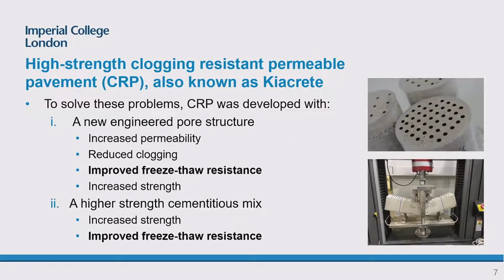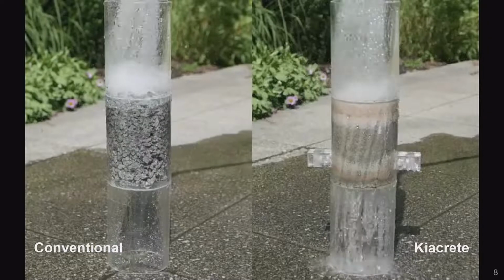So in order to address these two challenges, and also the freeze-thaw, which I will mention in a moment, we developed a new type of permeable pavement, which is called clogging resistant permeable pavement (CRP), also known as Kiacrete. So we completely changed the pore structure of this type of pavement. So we engineered a new type of pore structure, and we also are using a much higher strength cementitious mix. And this cementitious mix can be altered depending on the application. And in the past number of years, we've been doing a number of tests on it to understand its performance.